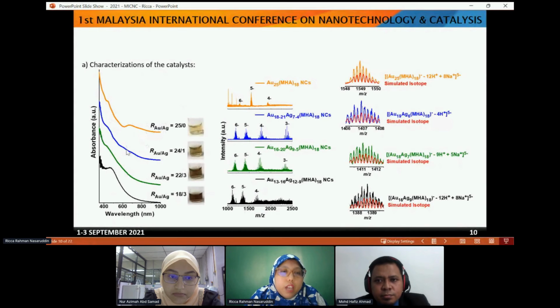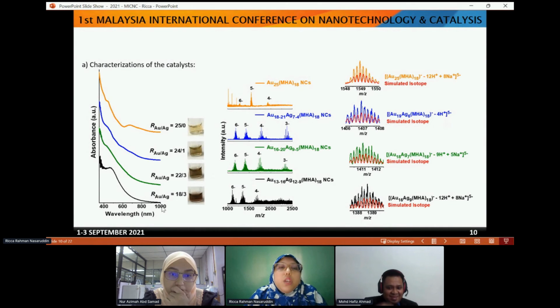But when you try to add this silver, like this one with this ratio 24:1, you can realize that you will get changes in the peak, especially at this 670. And then when you add more silver dopants, you can see the change in the peak at 670. And later on, when you go higher, the peak disappears, and then you have one peak here. So if you try to add even more silver, let me just show you later, you cannot get a nice